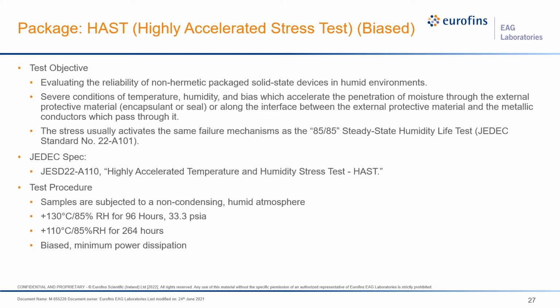The biased HAST, as the name says, is a bias test. The device should be in a low power state. The voltage levels on the I/O pins should be alternated between high and low levels as much as possible. Now, this test is designed for devices that are in a low power state that do not draw a lot of current. If the junction temperature of the device is 10 degrees greater than the 130C or the 110C, then the device power needs to be cycled on and off. This is to allow the device to cool enough to allow moisture to enter the package.